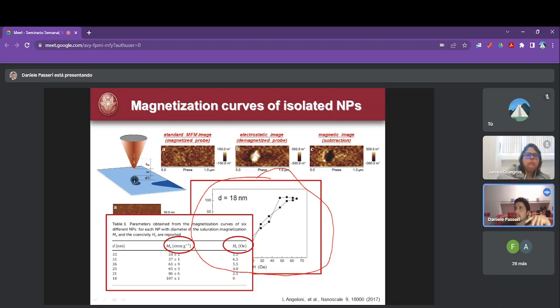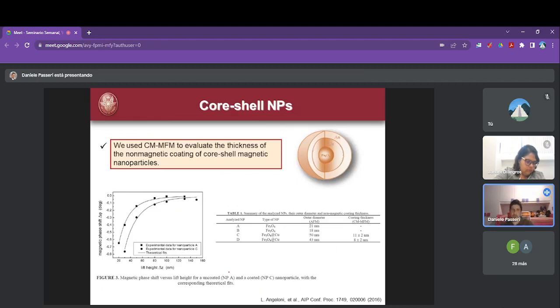Okay, this suffered from some approximation, and I don't want to discuss it too much. But also the coercivity. And it's very nice that even if the nanoparticles are very small, here you have a coercivity, which decreases here. So here you have the switching, in correspondence to about 20 nanometers, from a ferromagnetic behavior to a superparamagnetic behavior. I see that I'm wasting too much of your time, so let me just reach the conclusion.